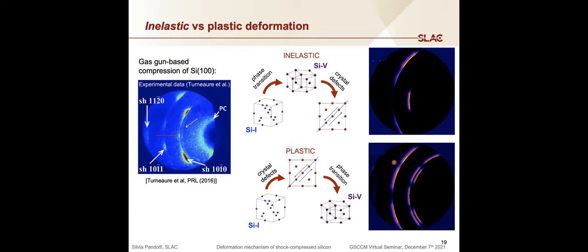And in this case, we do observe the presence of multiple orientations in data that can be much more similar to those observed by Turneaure. So it really seems that the presence of multiple orientation relationships can be directly linked with the plastic deformation regimes under gas gun shock compression, whilst when we perform experiments at a faster timescale, like in laser-driven shock compression, we do see the signature of the inelastic deformation.